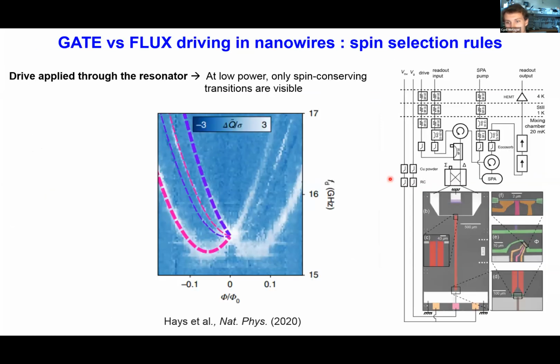Now, it was quite interesting for us to see that in a different group at Yale, using a different setup, they were also able to measure single quasi-particle transitions. But in this case, only the outer 2 transitions, the ones corresponding to spin-conserving transitions, were visible. And they could only evidence the inner transitions, the ones corresponding to spin-split processes, at the cost of driving strongly with a strong power. In this case, they were driving the system through the resonator, which is different to us, where we drive through the gate. And this told us that there seemed to be some spin selection rules at stake here.